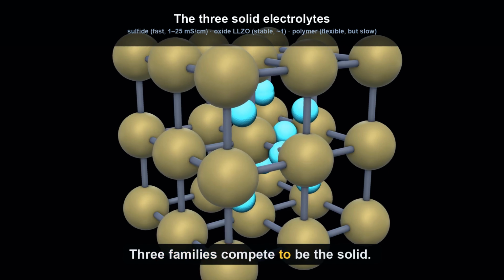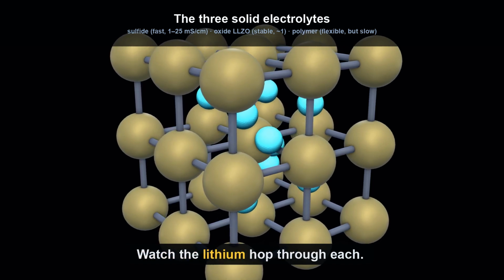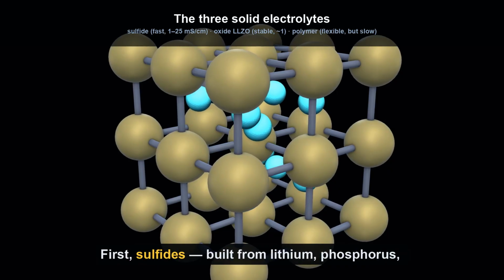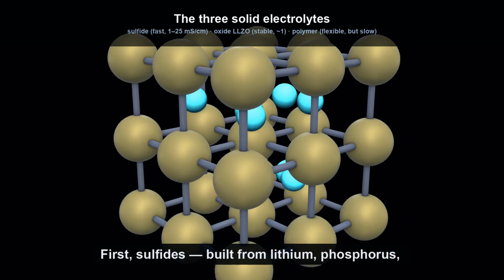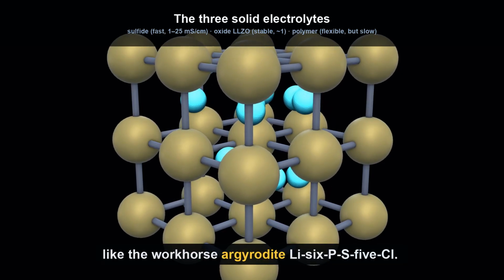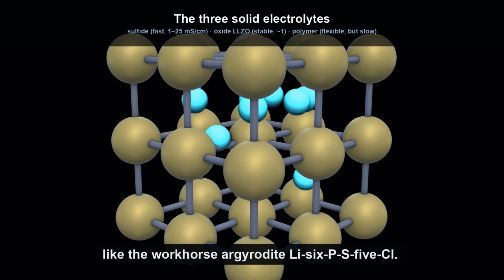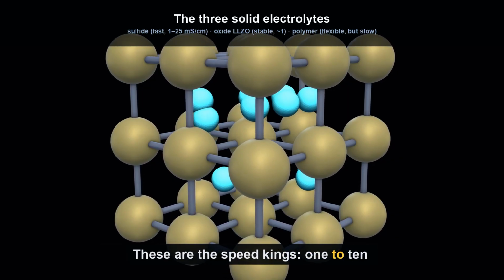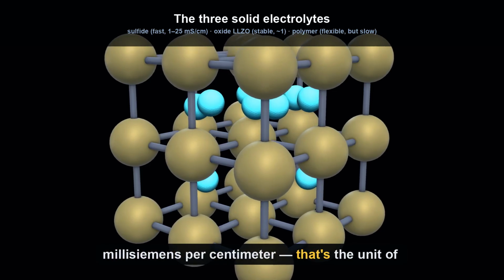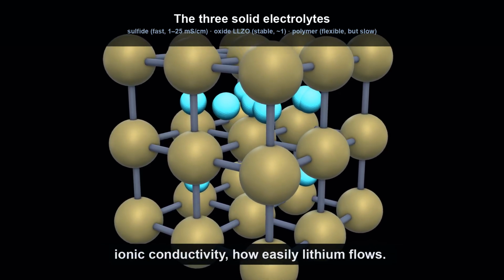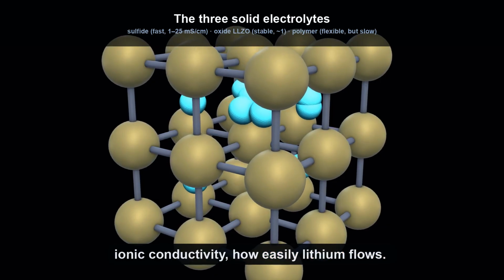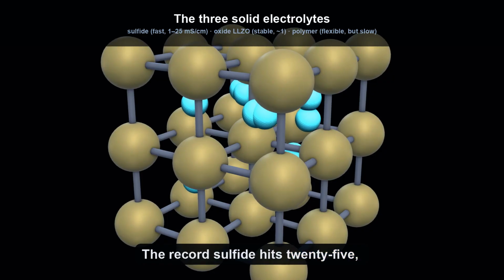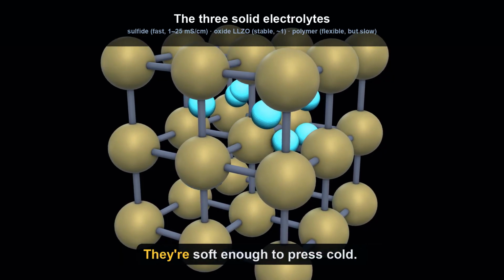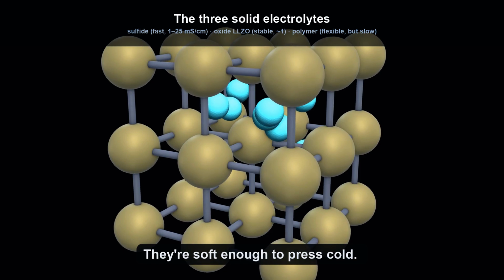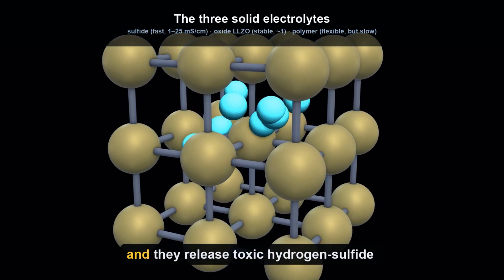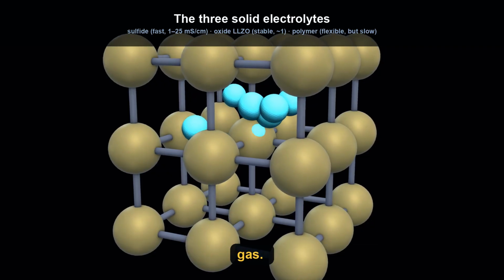3 families compete to be the solid. Watch the lithium hop through each. First, sulfides, built from lithium, phosphorus, sulfur, like the workhorse argyrodite Li6PS5Cl. These are the speed kings, 1 to 10 millisiemens per centimeter. That's the unit of ionic conductivity, how easily lithium flows. The record sulfide hits 25, more than twice the liquid benchmark of 10. They're soft enough to press cold. The catch: touch moisture, and they release toxic hydrogen sulfide gas.